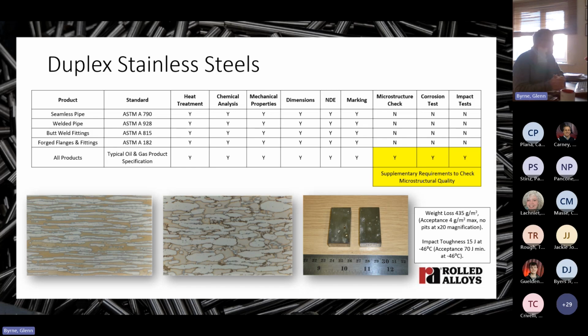Also, when we did impact toughness testing of this material, we got 15 joules at -46. Now, the acceptance level is typically 70 joules at -46, and for a structure like this, we would really expect toughnesses in the region of 150 to 200 joules at -46. So you can see that these properties are significantly deteriorated if sigma's present in the microstructure. Now, the problem is if something goes wrong in manufacture, these third phases that are formed, we've no idea that they're there unless we test for them.